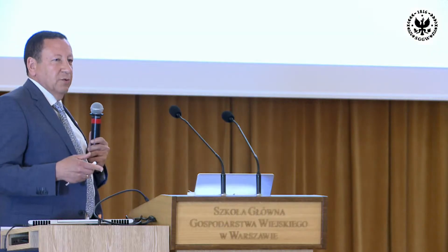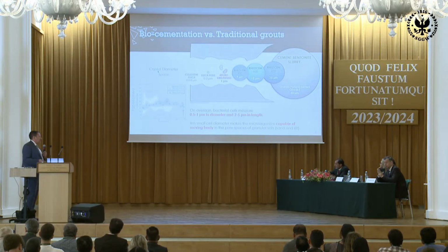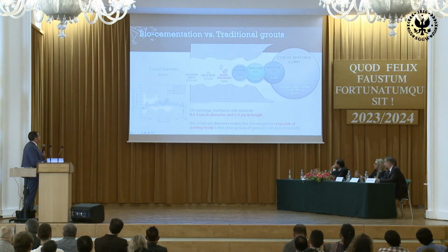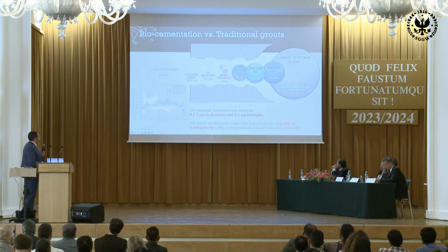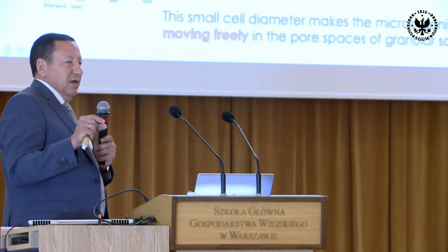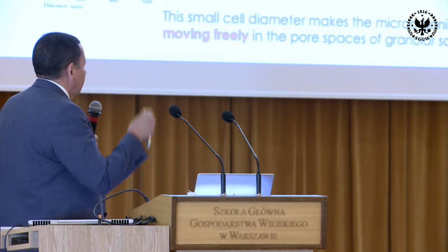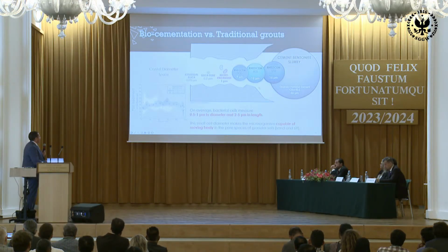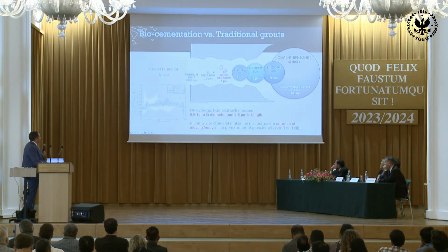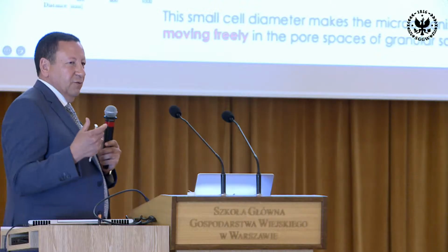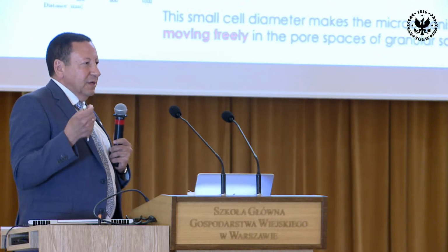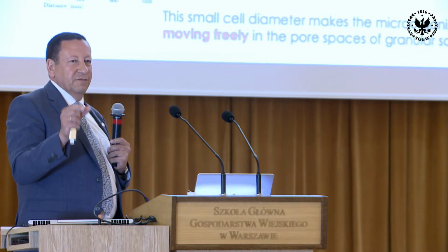So now if we compare this to conventional technologies and approaches, mainly using ordinary Portland cement, imagine this is a fracture, or this is the porosity of your material or your soil. Portland cement, the smallest size that you can reach is 40 micrometers. So you cannot inject below that. And then there are what we call micro cements that are meant for silty materials, for instance, where you can inject smaller things. In our case, we are going even smaller, because the limit for our solution is the size of the bacteria. The bacteria have a size between 0.5 and 1 micrometer.